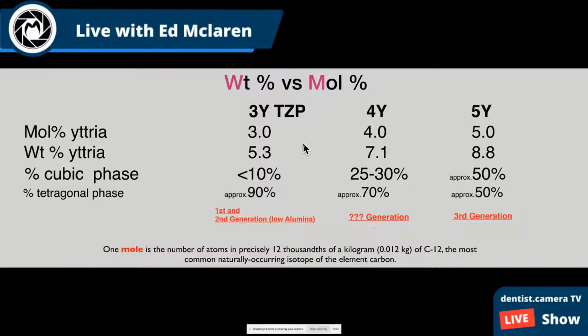So just a quick summary of what I just said. The 3Y material is the original high strength, virtually 100% tetragonal. The 5Y material came out right after that, okay? Medium strength, maybe a little on the low strength side based on zirconia, about half cubic, half tetragonal. All right, we go down to the 4Y, we decrease the yttria a little bit.